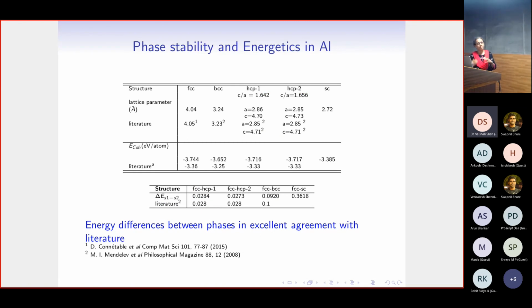So, as I said, when we develop the empirical potential, it should be developed in such a way that it works for a wide variety of properties that one is interested in looking at. That means in the fitting procedure, we need to include more parameters for which we do the fitting, and a step in this direction is to include the phase stability and energetics data. So for this we have done the ab initio calculations for the different phases of aluminum. We have compared them with what is available in the experiment or the literature, and how the differences between the phases compare with what is already reported. So this is the most important part.